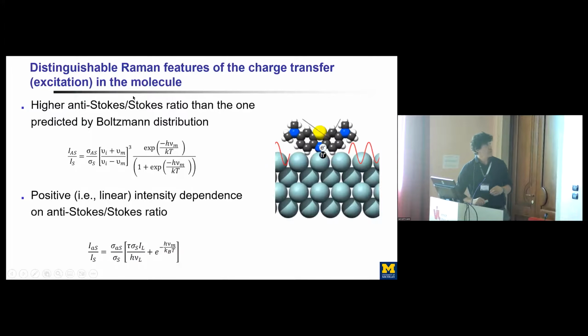In many of these studies, when you talk about signatures of this indirect charge transfer or direct charge transfer at the interface, one signature is that you would have a higher anti-Stokes to Stokes ratio in this Raman measurement than the one predicted by the Boltzmann distribution. So in other words, if I have an excitation of an electron or a hole, and it goes through this anti-bonding or any orbital in this dye molecule that's sitting on the surface, because of the difference in the heat capacity between the nanoparticle and this molecule, I'd expect this molecule to get hot.